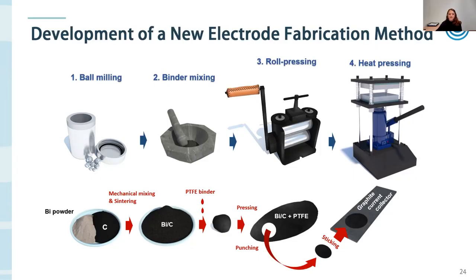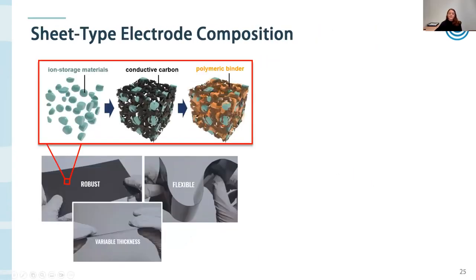And so using this new electrode fabrication method, we've created this carbon and polymeric binder framework around our active materials to kind of keep everything together. And when we look at these electrodes, we find that they're really flexible and robust. They have a really high mechanical strength. They almost have the consistency of a really thin sheet of rubber, but are very conductive.